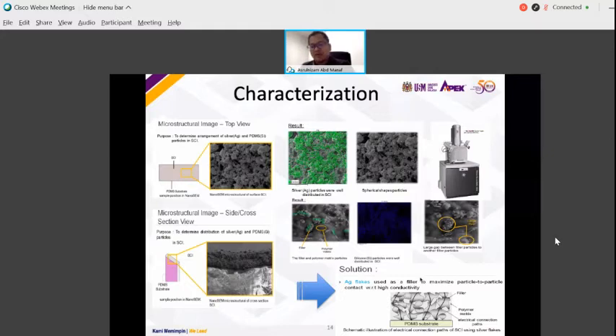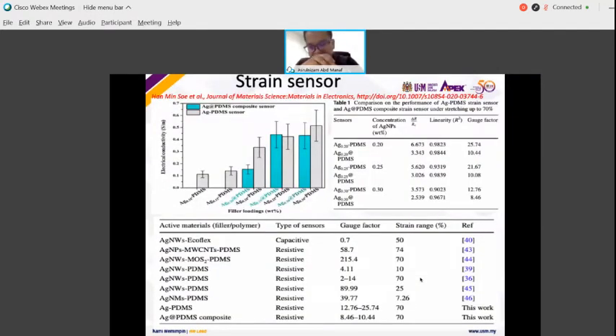We have the trade-off between what is the suitable silver nanoparticle ratio with the polymer, in our case the PDMS, to improve the ink conductivity. Of course, we have the baseline with copper, that means 10 to the power 6. That's good conductivity, that we can implement in our PCB fabrication. So this is some of our studies.